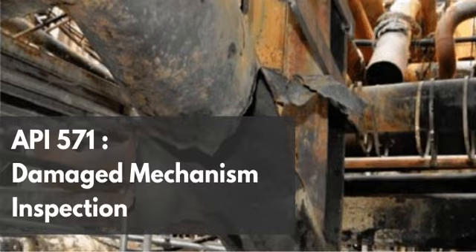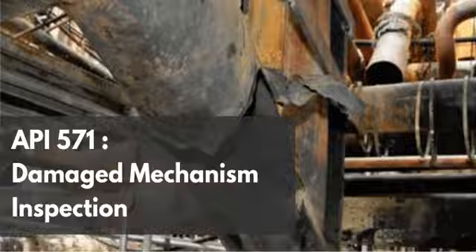And that phrase right there, sound metal wall thickness, that is the absolute nightmare for an inspector. Why is that? Because it means that even if you measure the physical pipe wall and it's still a beefy, say, half-inch thick, the portion of that wall that has been carburized, maybe a quarter of an inch deep, can no longer be relied upon. It's structurally dead weight.